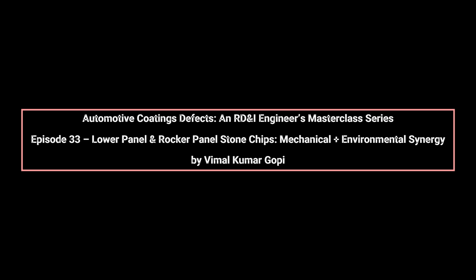From a troubleshooting perspective, addressing rocker panel chipping requires a system-level approach. Engineers evaluate primer flexibility, total film build, curing profiles, spray uniformity, and substrate geometry. Process adjustments may include localized film build increases, modified spray paths, or application of protective coatings or films in high-risk areas. Lower panel and rocker panel chipping is not a single defect, but a failure cascade.